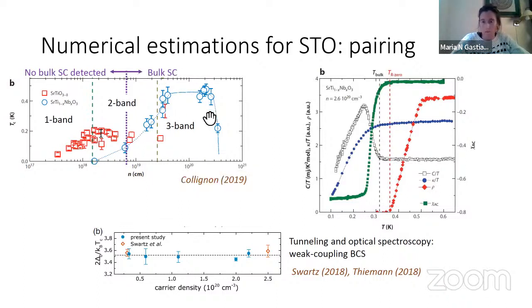When you are in this optimal doping, it still is quite dilute, small fermions and all that, but I'm showing here the typical measurements that signal the transition into the superconducting phase. You have the specific heat jump here, you get the magnetization here, and resistivity dropping to 0 happens at slightly higher temperatures. That's a common feature in all this area, but nevertheless, you do get bulk signatures.